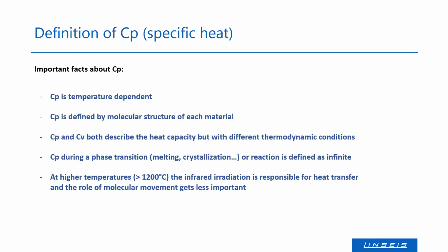And what's also important, CP is often hard to measure at really high temperatures. Here, the infrared irradiation is the main thing for the heat transfer, and not the heat transfer between the sample crucible and the measurement system anymore. So it's hard to detect valuable CP values here, but most DSCs, or the standard DSCs, are limited to 600. So it doesn't matter here, but of course also at 600 or 700 degrees it has an influence.